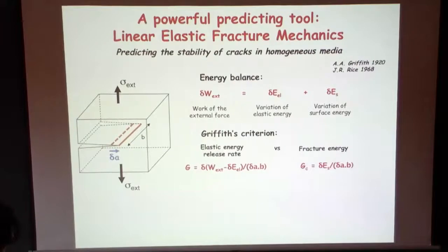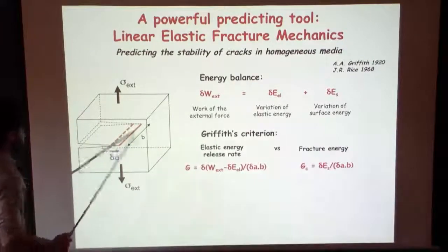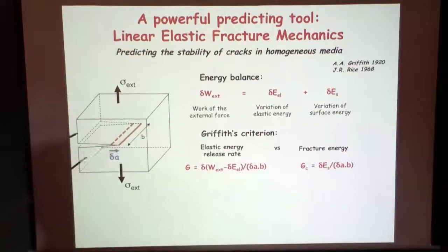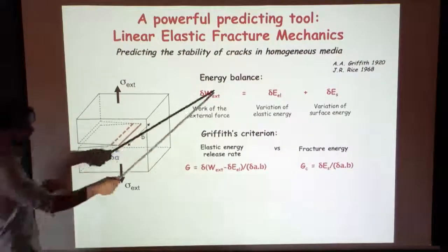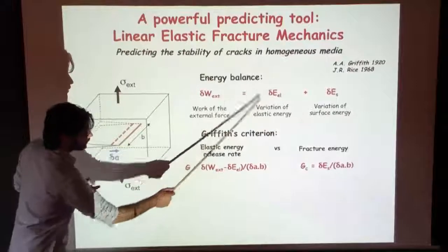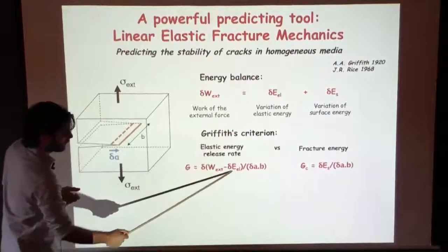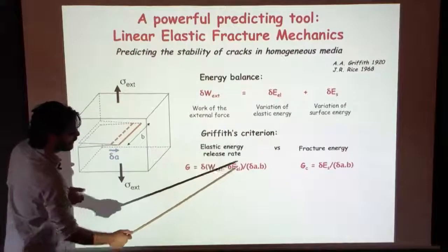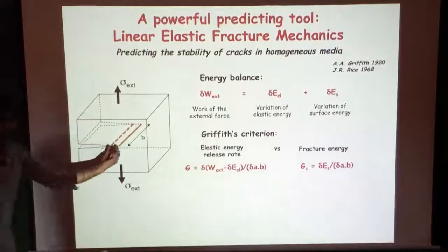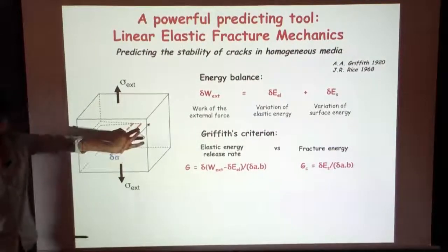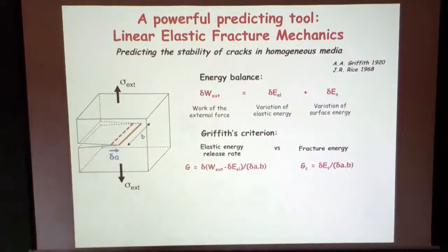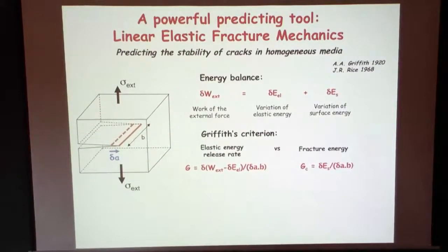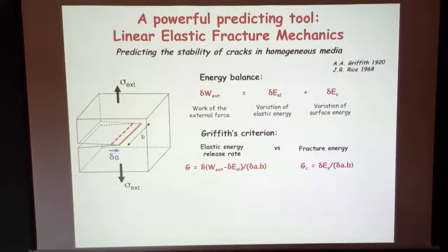And the idea to look at this problem is not to look at energy variation, but the rate of energy dissipated, the rate of energy released. To look at rate, you're going to gather these two terms that correspond to the mechanical energy of your system, and look at the variation of this term normalized by the surface of propagation, delta A times B. It's a rate of variation of mechanical energy as your crack propagates over some unit surface.